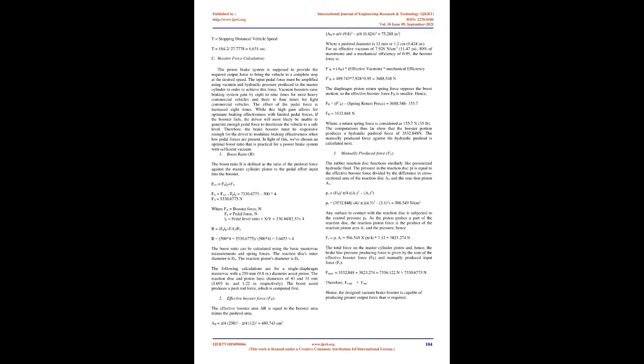The main source of concern is low vacuum pressure from the engine. A loose or cracked hose, which lets air into the system, is typically the problem. Vacuum leaks cause the engine to idle poorly and pause while accelerating. Another issue is a large internal diaphragm in the vacuum brake booster gets hardened and develops internal leaks over time. This problem is much more prevalent in cold, dry climates. However, the larger the diaphragm, the greater the amount of power assist. To solve this issue, we have designed a large-sized diaphragm with appropriate material.